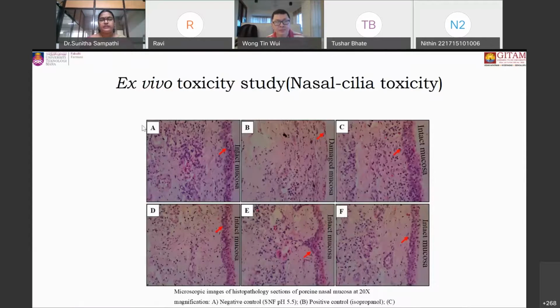After this cytotoxicity study in the cell lines, we took it forward for the ex vivo toxicity studies, which is also called a nasal ciliary toxicity study. Here we have done this study in the nasal mucosa of the porcine, that is the pig. We exposed the formulation to the nasal mucosa of the pig, and then checked for damage of the cilia. A is a negative control, exposed to saline, B is a positive control, and as per the literature, the positive control is always maintained by isopropanol, so we used the same here.